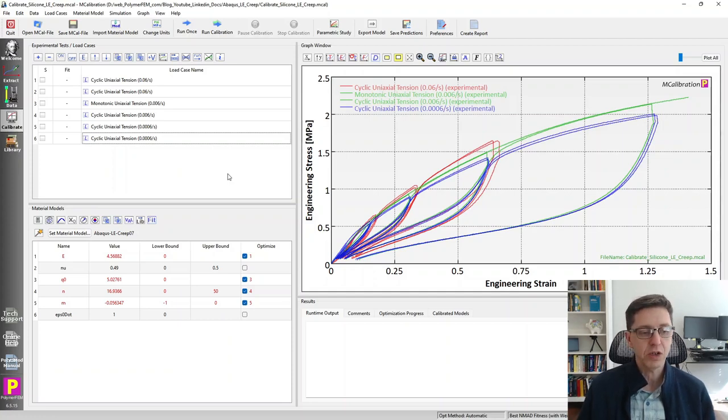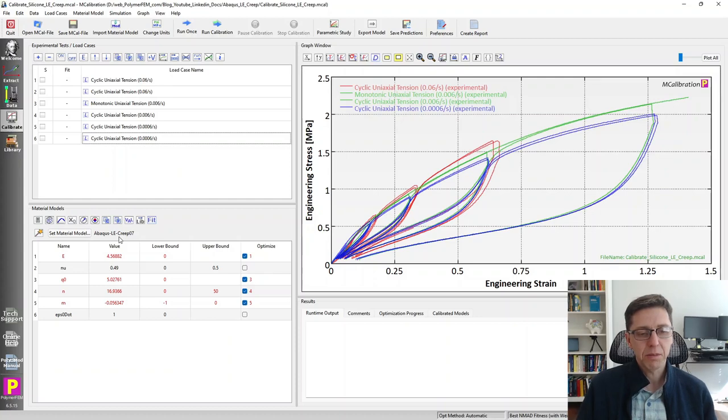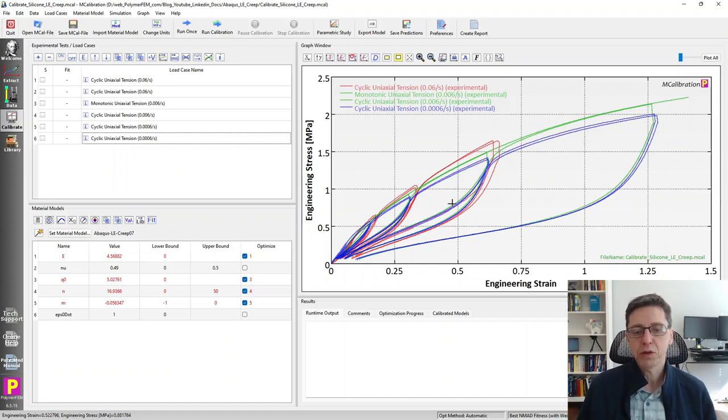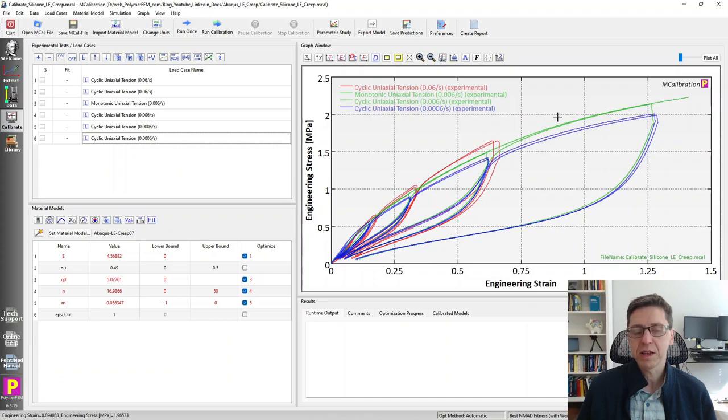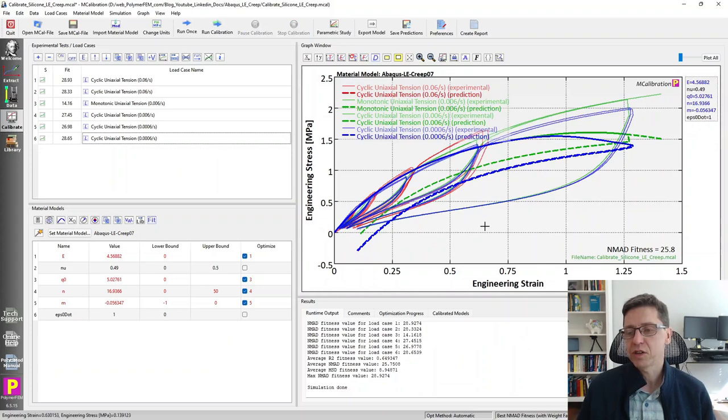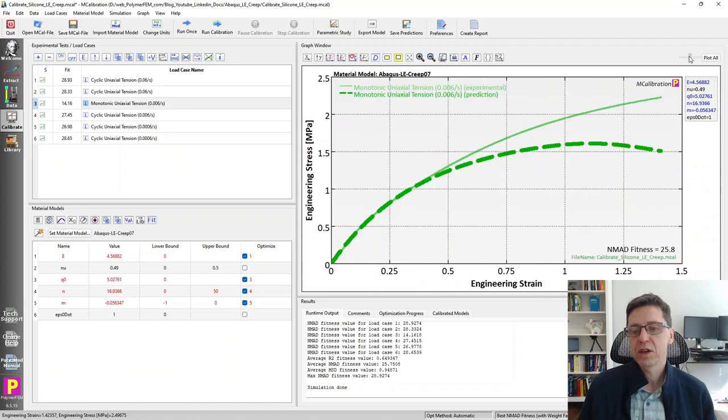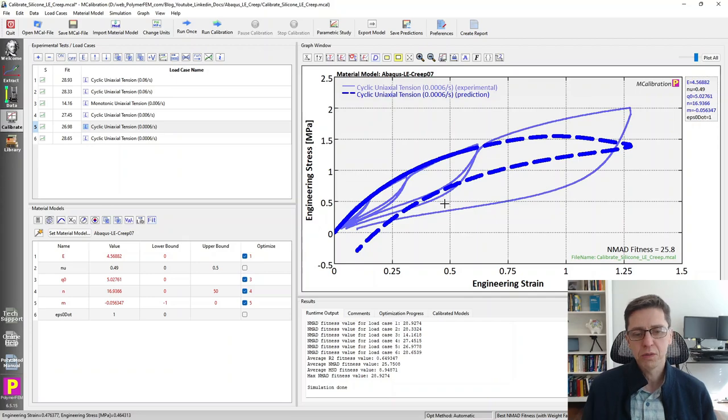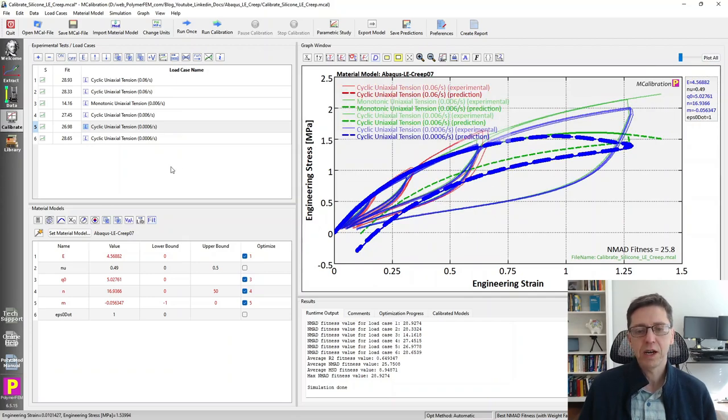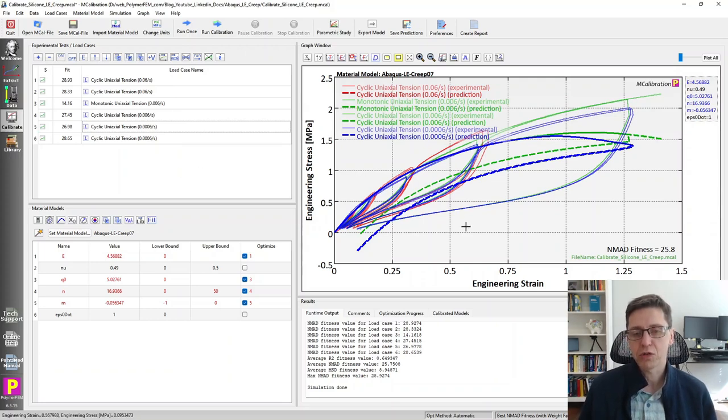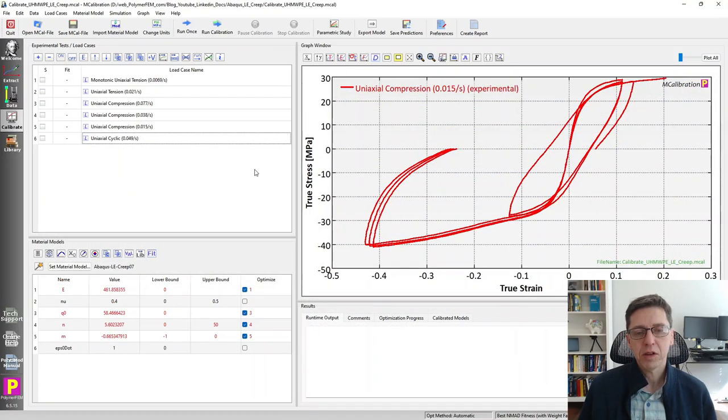The next thing I want to show you is a little bit about, can we use these for different polymers? Do they work? Is this a good idea? So I'm using here a linear elastic material model in Abaqus with the strain-based power model, and I calibrated it to experimental data. In this case, it's for silicone rubber. So I have experimental data, load and unload cycles. This is experimental data, and the best fit I can come up with is as you can see here. So the error is 25.8% and the predictions are kind of goofy. They look kind of in the middle here, but you can see that it doesn't look like it should look when you know the experimental data. So I would not recommend using this kind of linear elastic with creep model to predict this kind of larger strain response of an elastomer.